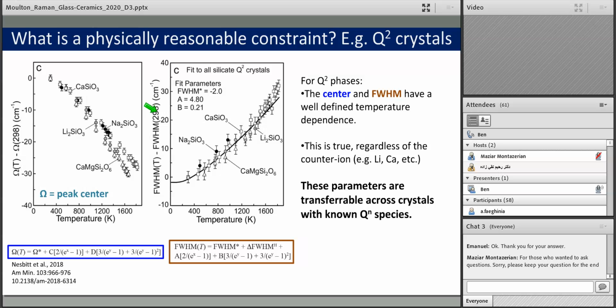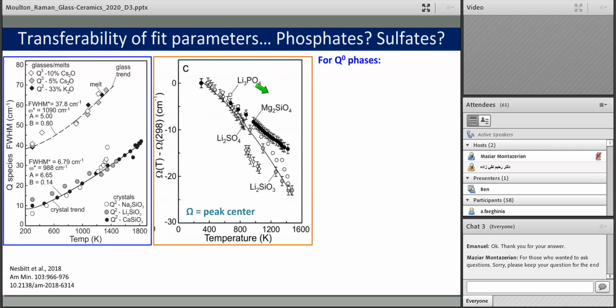But in both cases, you see that both the shift in the center as a function of temperature and the full width half max shift consistently, despite having different symmetries and different chemistries. Again, calcium, lithium, a mixture, magnesium, calcium, sodium, they're all following the same trend. So this gives me confidence that there's a systematic behavior in these stretching modes for crystals. And let's see how that compares to some glasses.